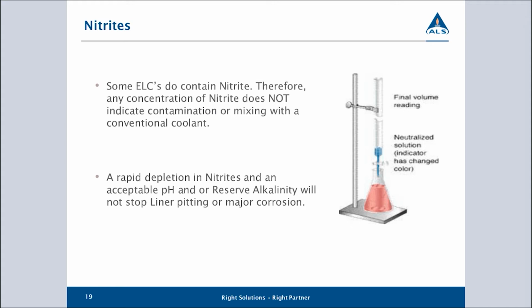If you see a rapid depletion, it means that there is something that's trying to drive a lot of corrosion in your cooling system, and this means two things: that you may have a problem with the cooling system and it may be running too hot or overstressed. It could also mean that whatever else you have in that coolant that should be inhibiting corrosion is not working. So if this is a hybrid style coolant, it means that the organic acids are not doing their job. This could be through cavitation. This could be through excessive vibration. It could be through electrical current. There's a range of things that can cause this to happen, but it's an early warning indicator that this coolant is not surviving very well in that environment.